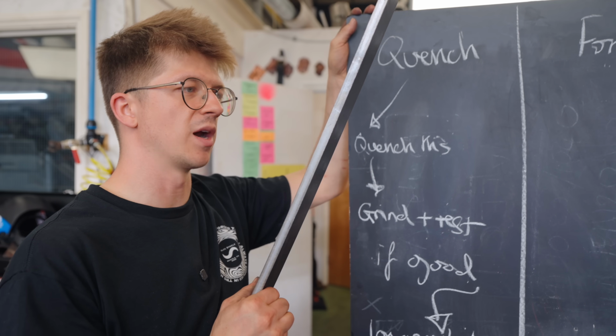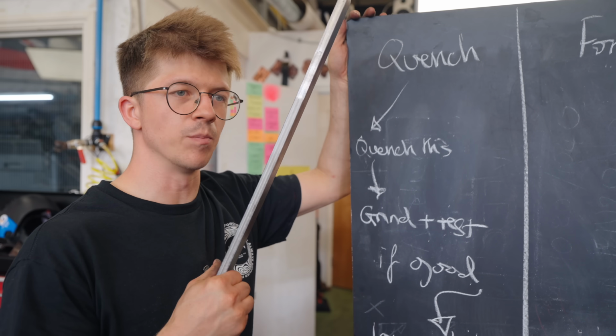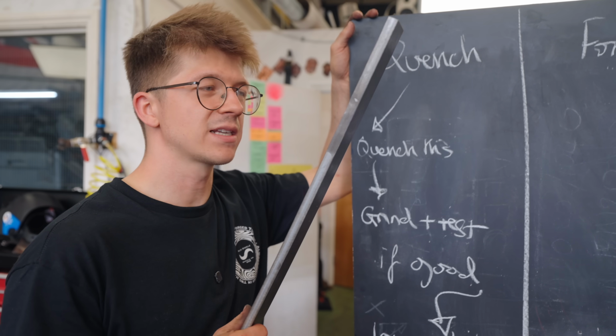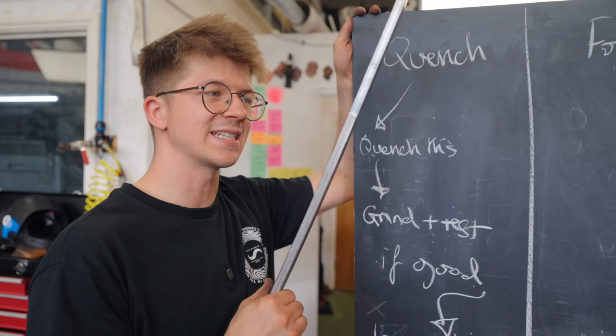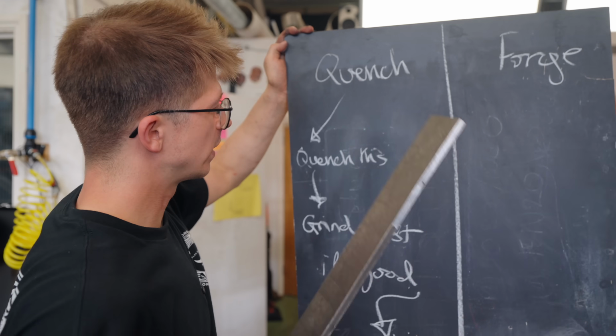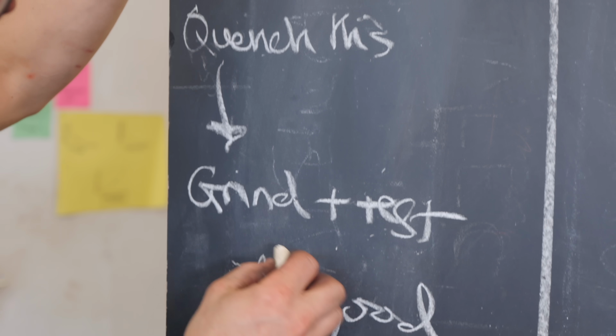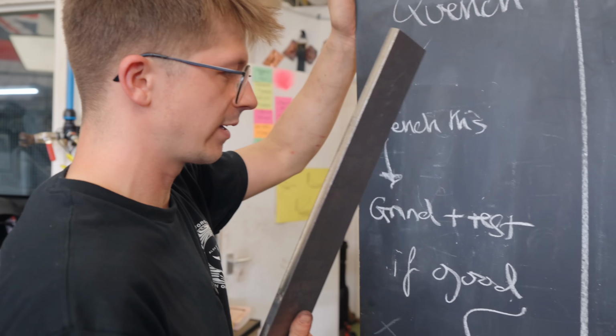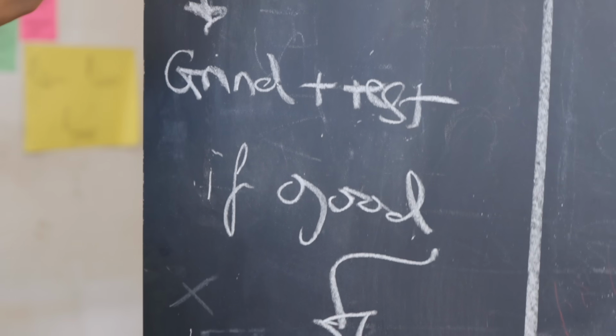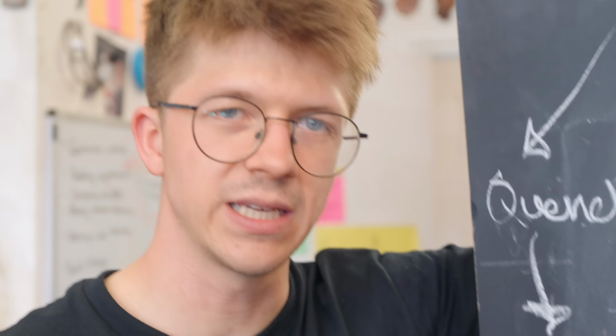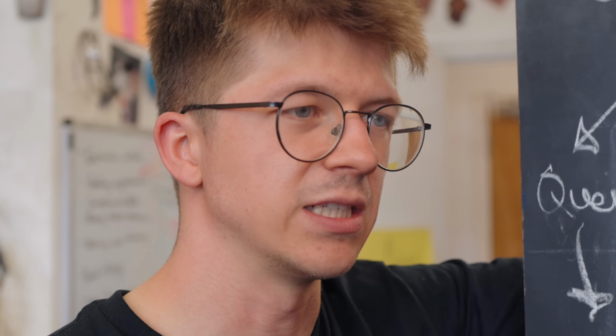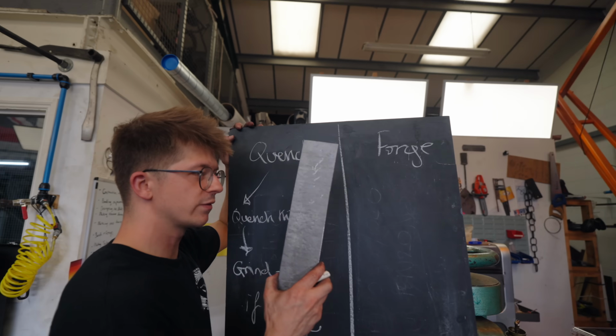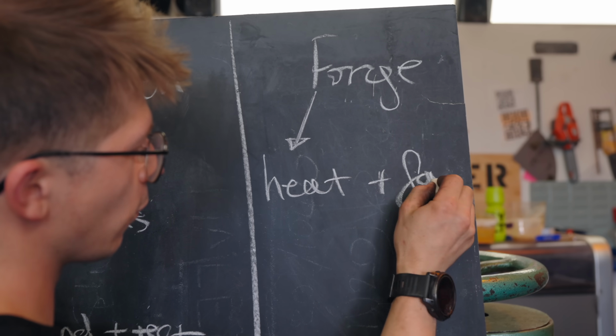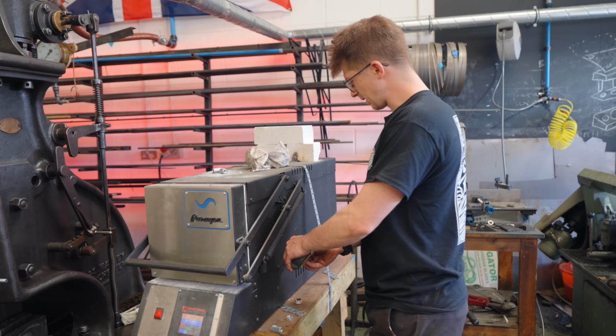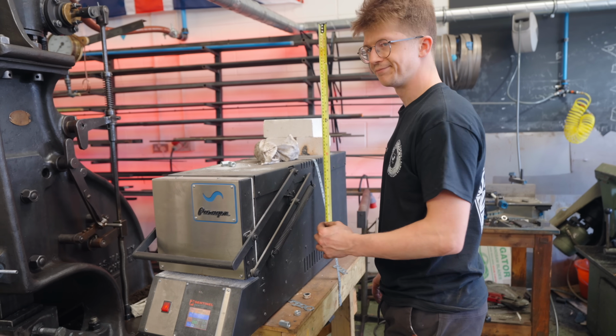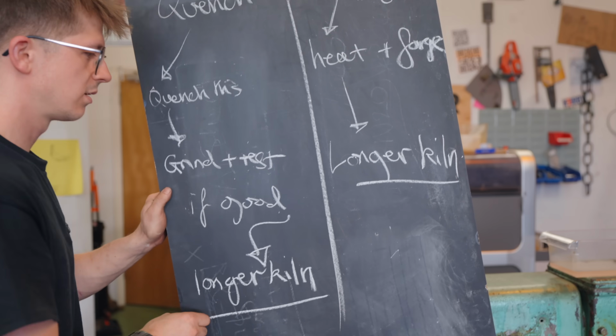If I quench this experiment, what we're demonstrating is that we can bond a big slab that needs to be as long as the finished katana, and we will then heat treat it in its big slab state before we cut out the katana. So with this piece, I would then quench it, and then grind down the sides so that we get it to the final thickness, test it, and if it's good, I'm gonna need a longer kiln to be able to heat up, bond, and heat treat our final katana dimensioned piece. Now, if we want to forge this piece, we can heat and forge. It's currently 49 centimeters. We'll be able to increase its length about that much. That also means we need a longer kiln.